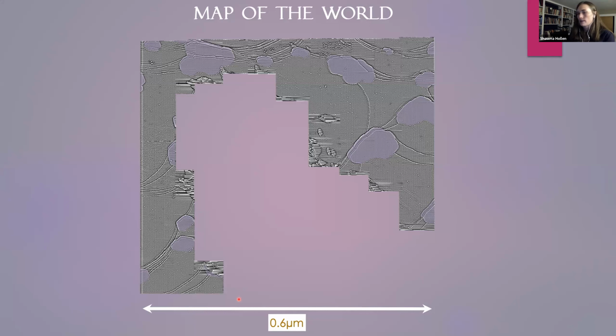And you'll notice that at the edges, there's a whole huge gap in the center of this image. And every time that we get close to this empty region, there's a lot of stripy stuff, okay? All of that stripy stuff is a tip sample interaction, meaning that atoms are jumping back and forth from the tip to the sample and messing up the imaging. Now, if too much of that happens, your entire experiment is over and you have to just start new. So we avoid this region whenever we see bad imaging, like the edges of this huge square here. We just move away, keep to the easily navigable areas.